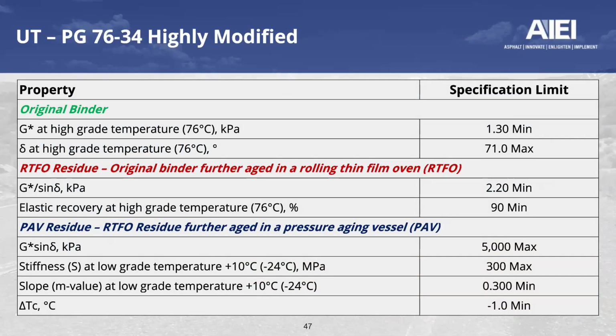Being happy with that work, work continued within the lab, and Howard Anderson and his crew continued to refine their specification. And this is the current binder specification for the 76-34 binder. Note that on the original binder, they have a G-star requirement, minimum of 1.3. In this case, that test is run at 76 degrees, the high PG grade. That is a consistent requirement for all PG grades in the state of Utah. They conduct the test at the high PG grade, and they have to have a minimum of the unaged material of 1.3. There is a high temperature delta requirement of a maximum of 71 degrees.